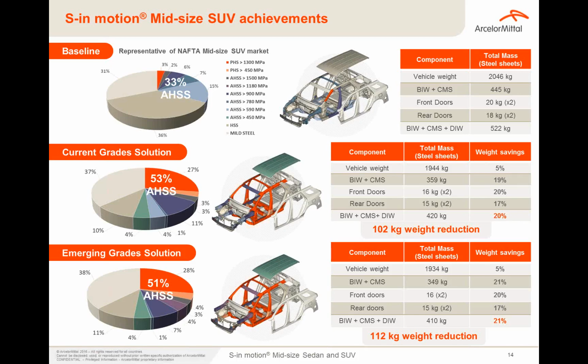We have also developed, as we said at the beginning, a solution with emerging steel grades. And here you see that you can add additional weight saving, up to 112 kilogram weight reduction, with Usibor 2000, Ductibor 1000, and the Fortiform family, which represent a very high amount of advanced high-strength steels at the end. And here you can see on the pie chart that for emerging grades, we have chosen to push a very aggressive scenario with press hardened steel that represents more than 30% of the body-in-white structure.